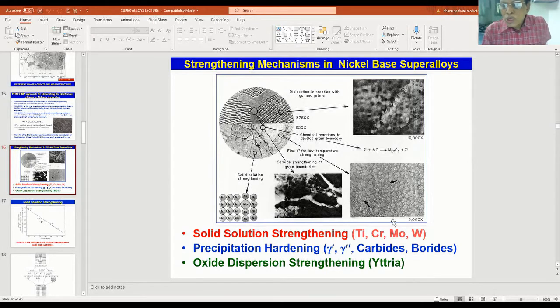And here you have the two types of gamma prime, fine gamma prime as well as coarse gamma prime, which depends on the temperature that you employed during the heat treatment. This precipitation hardening of the matrix is derived from the gamma prime and gamma double prime phases. And carbides form on the grain boundary, and then they strengthen the material against creep. Once these carbides are distributed on the grain boundary in a discrete manner, they restrict the sliding of the grain boundary and will not allow any cavities or cracks to form in the material.